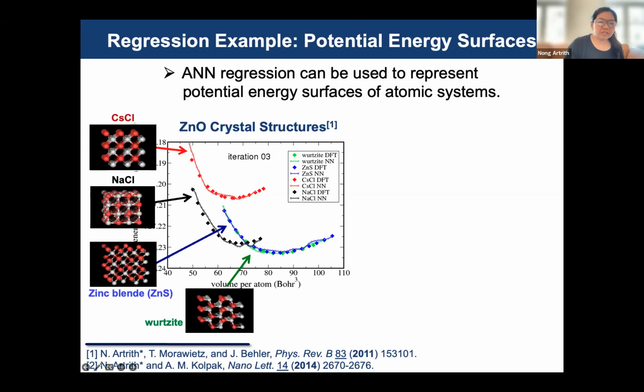So we have the red is oxygen and the gray is zinc. There are so many different phases that you can see with the high energy structures and also lower or more stable crystal structures. So we collect the DFT database, for example, in isolated molecules or periodic structures and also surfaces, and then use it to train neural network potentials. And then we predict the crystal structures.